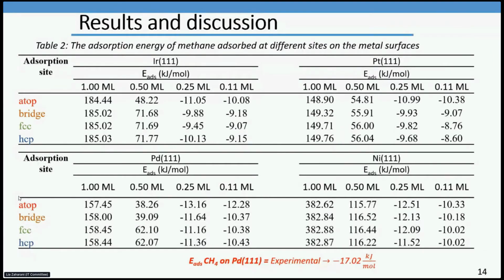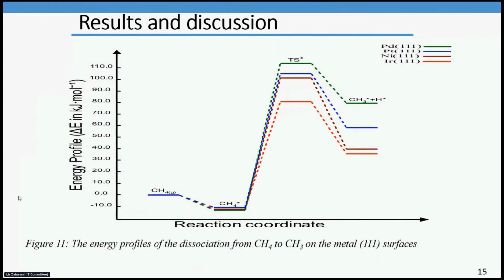From this table, methane has the strongest interaction with the palladium (111) surface. The methane interaction with the metal surface is very weak, which indicates physical adsorption. This figure shows the energy profile of dissociation from CH4 to CH3 on the metal (111) surface. The methane dissociation is preferred on the iridium surface than on the other metal surfaces.